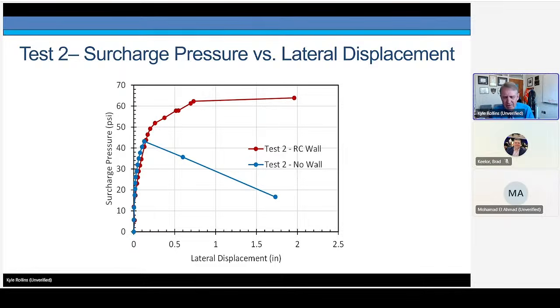This is showing the surcharge pressure versus lateral displacement. And again, the two curves are very similar until we get up to 44 psi, and then they start to diverge. We start to get a lot of lateral displacement post-peak, and we have a reduction in the surcharge pressure that we can maintain. In contrast, with the RC wall in place, again, we get an additional 20 psi before we start experiencing significant lateral displacement. And this added capacity is coming from the moment that was provided by the stem wall and the reinforcing steel that helps produce that. And since we're dealing with the steel, it's a much more ductile failure situation.